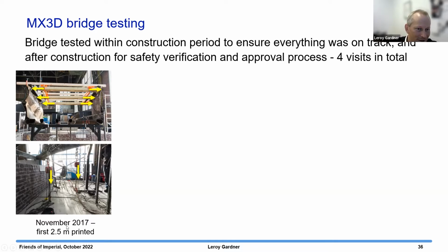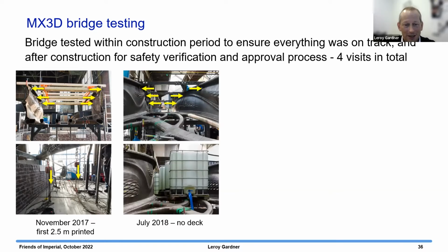So this process started at the end of 2017, and the first 2.5 meters was printed at that stage. And we had relatively crude loading equipment that we took over to Amsterdam and carried out some tests, took some measurements, and it was performing well and performing roughly as we'd anticipated from a finite element model that we'd created. We went a second time in July 2018 when the full length of the bridge had been printed, and you can actually see the substructure here, which is an interesting sort of organic shape.